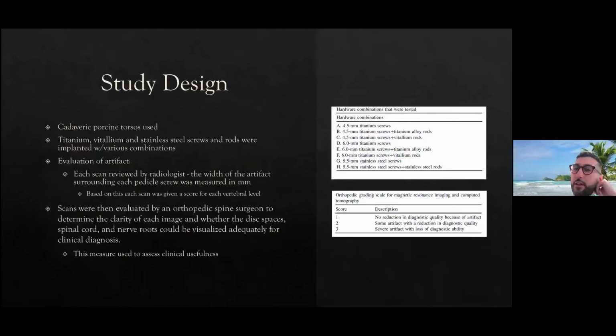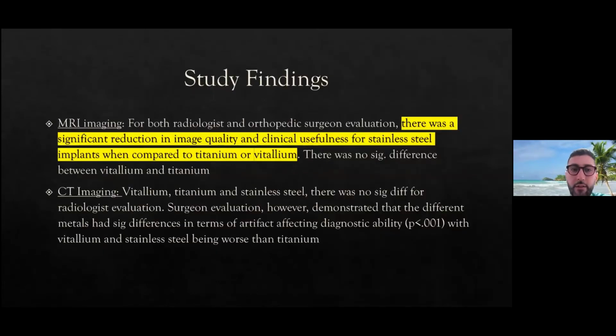But basically, this study used cadaveric porcine torsos. They implanted them with various combinations of titanium, vitallium, and stainless steel, and they evaluated the artifact. And they had a radiologist review it. They also had an orthopedic spine surgeon. The radiologist was looking at the width of the artifact, and the orthopedic spine surgeon was looking at whether it resulted in a significant ability to clinically assess patients, its clinical usefulness. And here's a grading scale that they used.